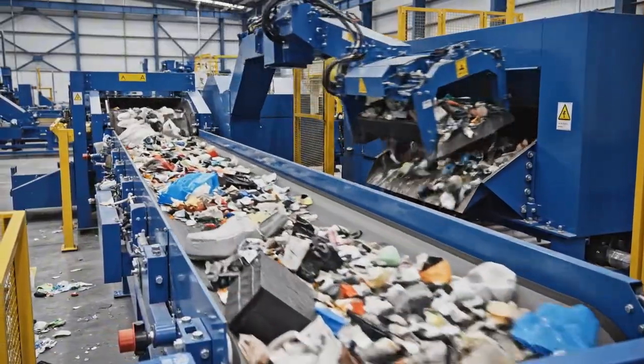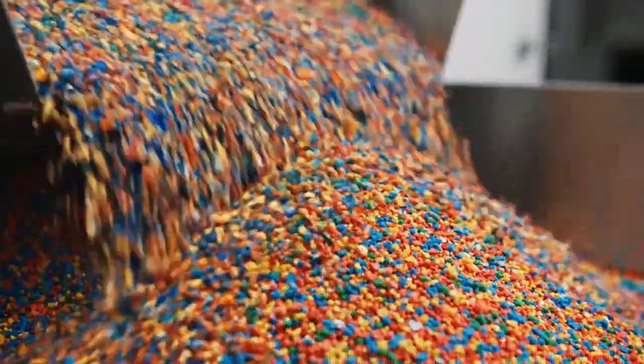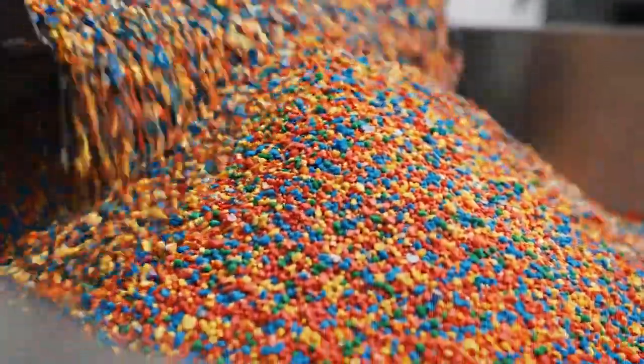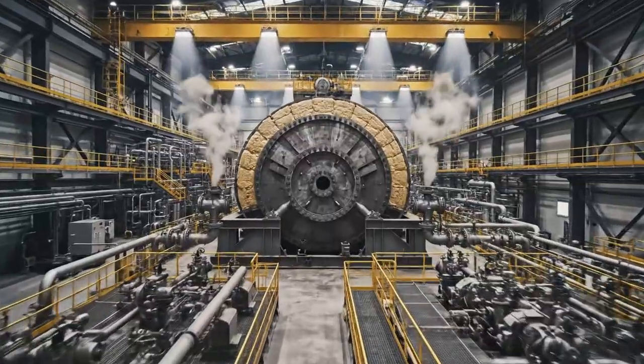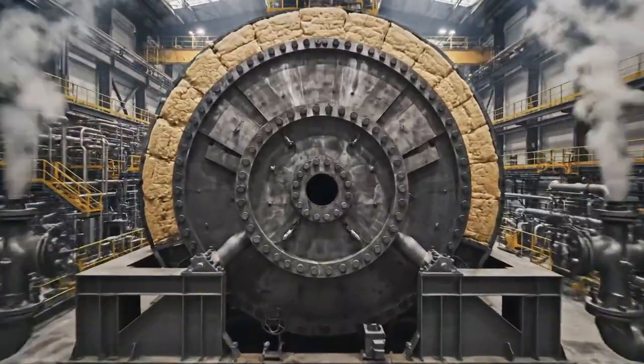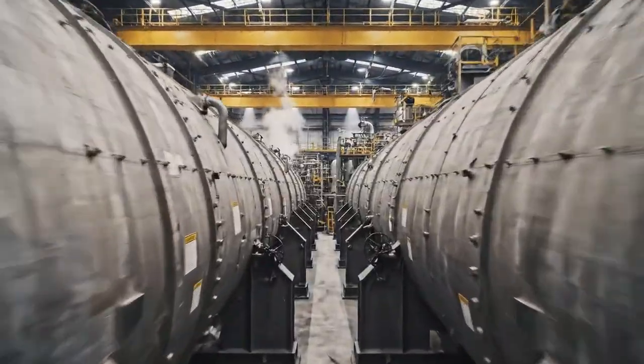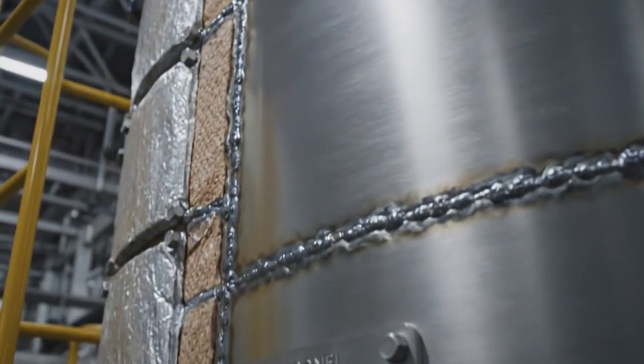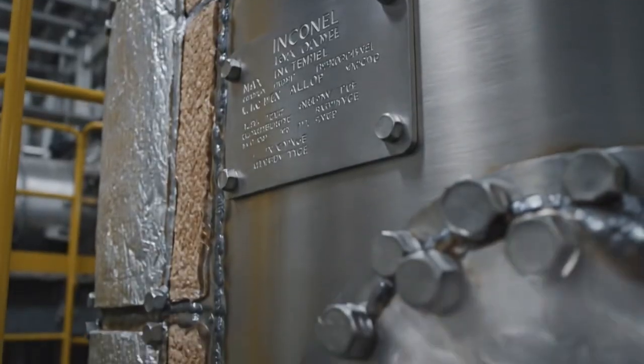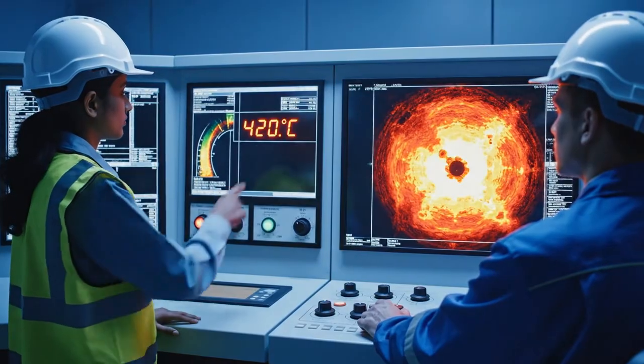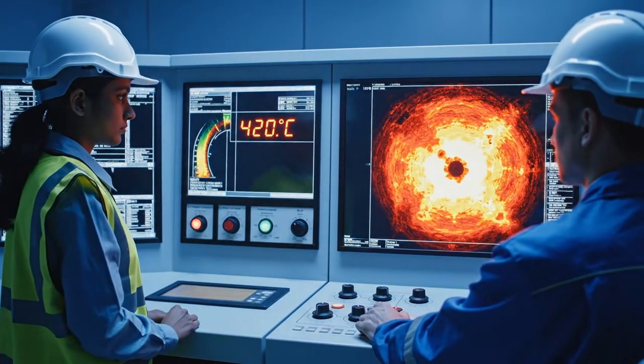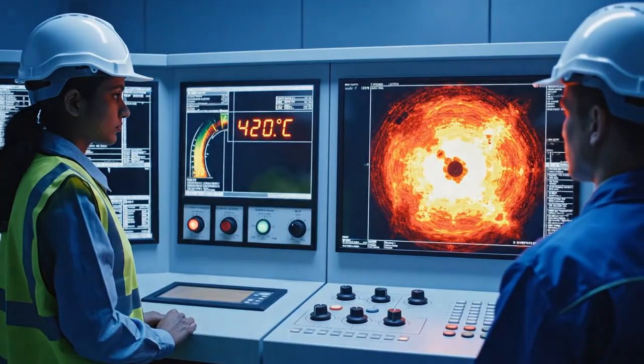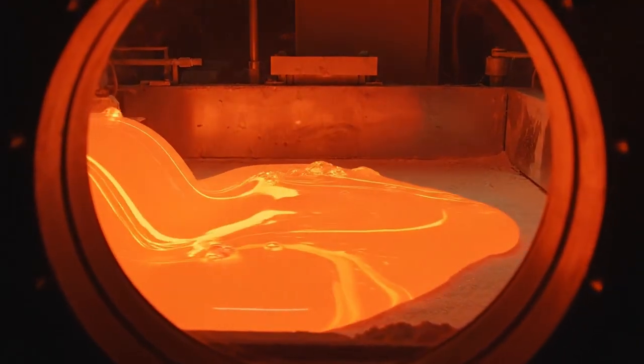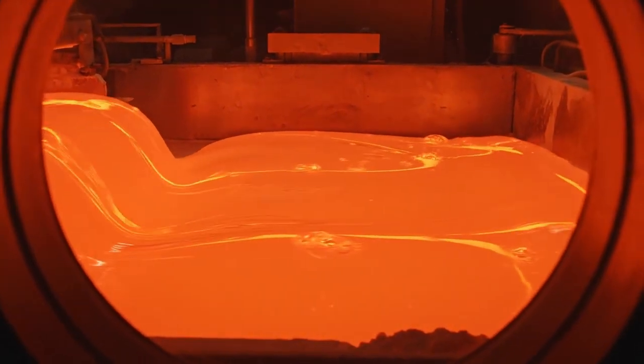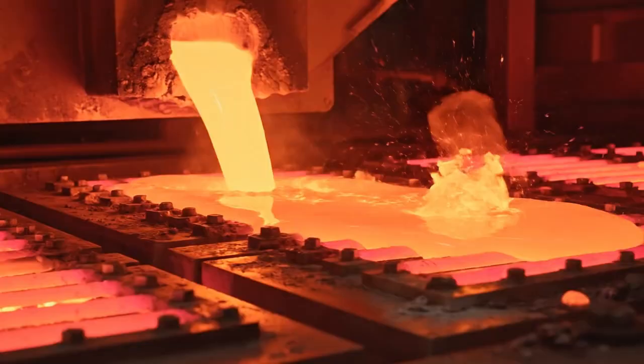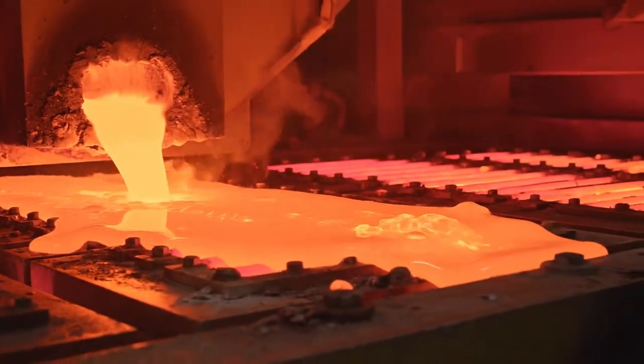The result is a coarse powder the color of confetti, a homogeneous mass that betrays no hint of its former identity as interlocking bricks. This powder enters the thermal decomposition reactor, a sealed chamber where temperature and pressure become instruments of molecular surgery. The reactor is a horizontal cylinder, 10 meters in length, lined with Inconel alloy to resist both heat and chemical corrosion. Inside, the temperature climbs to 420 degrees Celsius, hot enough to soften the ABS plastic, but not hot enough to trigger complete pyrolysis. The powder liquefies, becoming a viscous resin that flows like lava across heating elements embedded in the reactor floor.